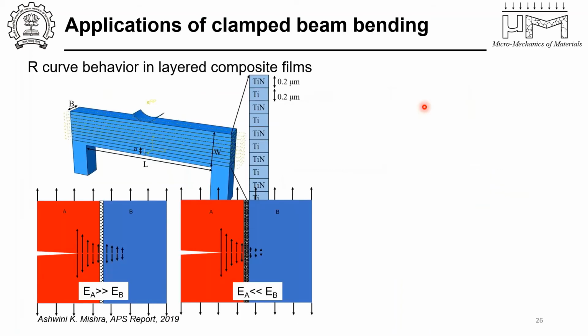The third thing that we are also interested in looking at is how the R curve behavior affects a layered composite film. Let's say you have a multi-layered material. One is a ceramic, hard and brittle, and one is the metallic layer. Individual layer thicknesses are very fine, and the total thickness itself is about 2 to 4 microns. We wanted to again take up this geometry to look at what kind of stabilization, what kind of R curve behavior or resistance to crack growth this multi-layering will provide.